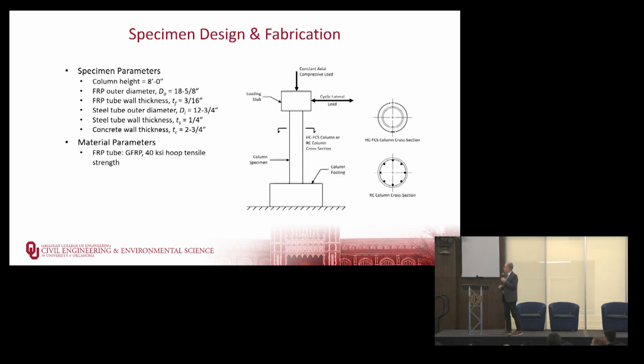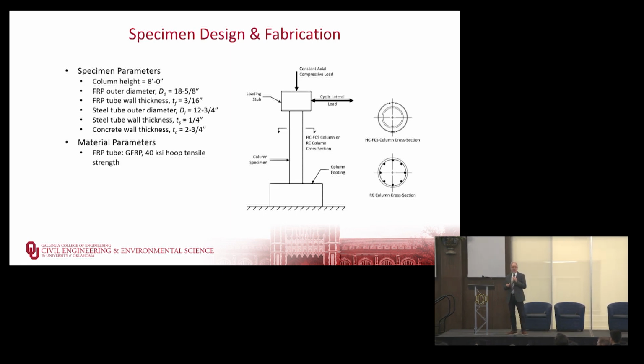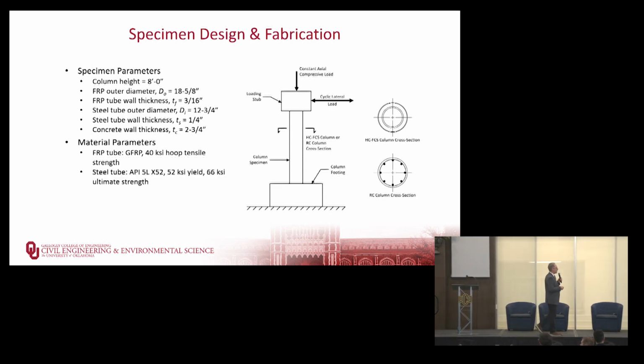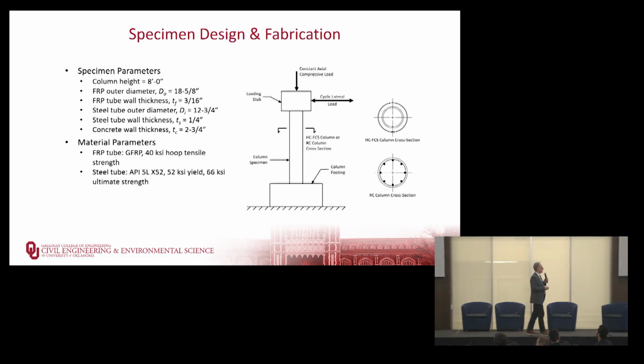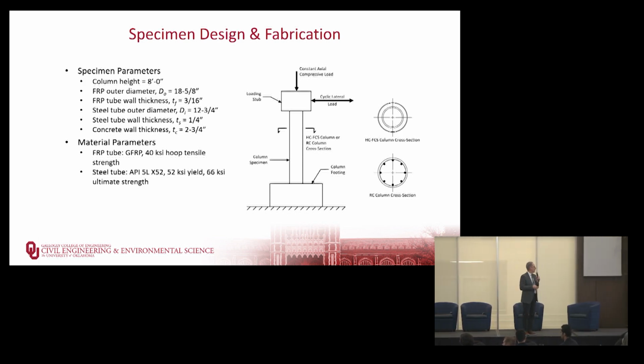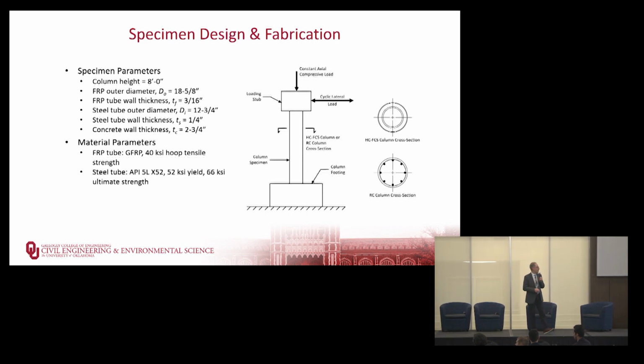The FRP is glass fiber reinforced polymer, standard tubes, 40 KSI hoop stress. And then the steel tube has a yield strength of 52 KSI and an ultimate strength of 66 KSI. So we're going to put a nominal axial load on these specimens and then push them back and forth in a cyclic loading.